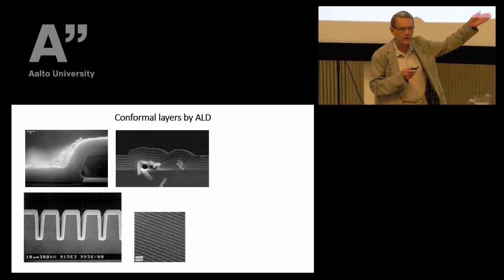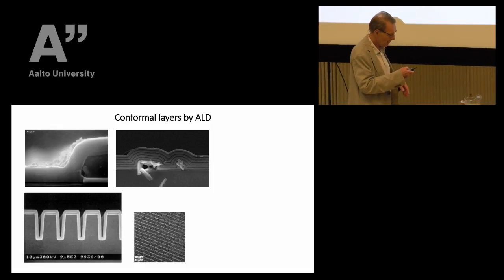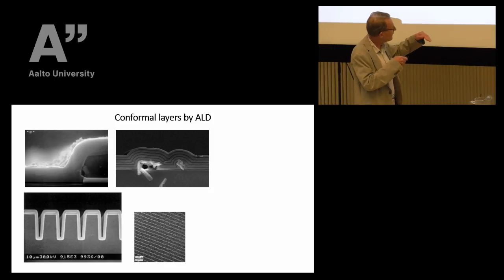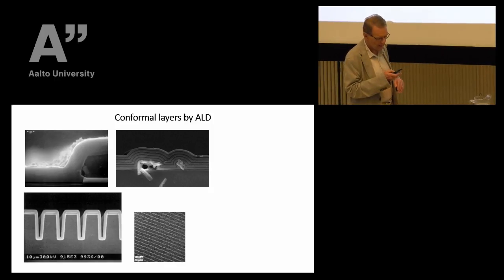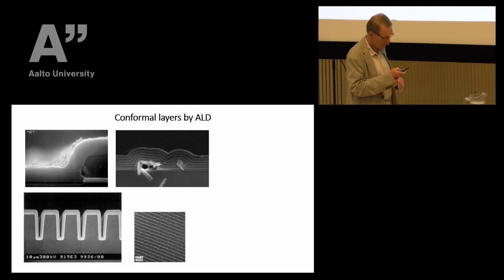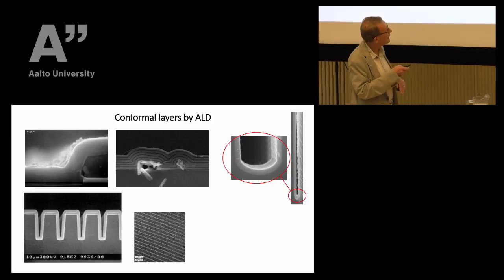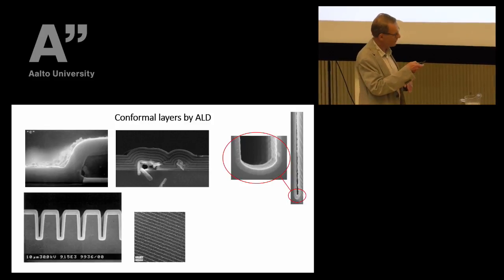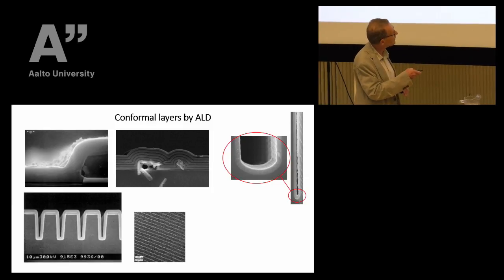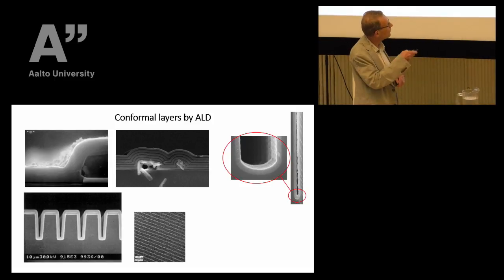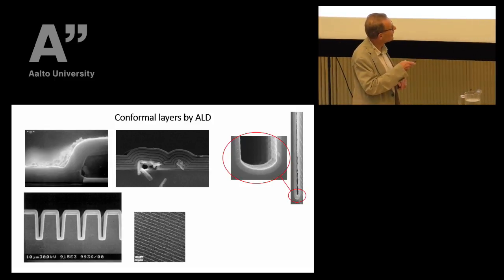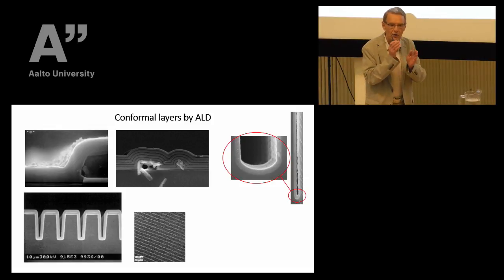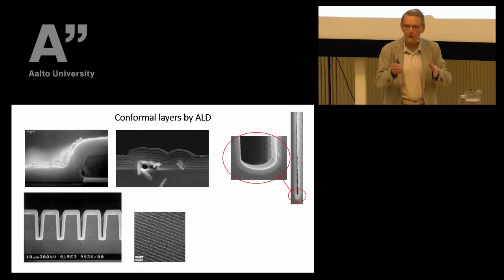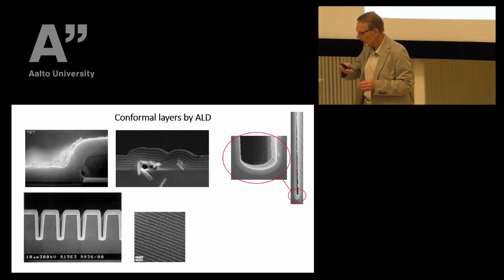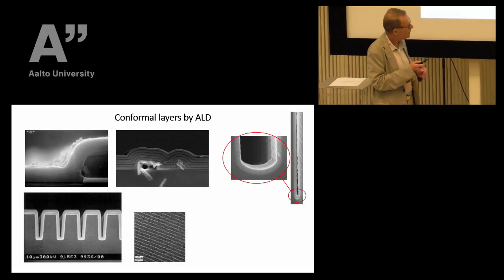Also, we can tailor materials, so it's kind of a superlattice that we can change the material type even at each atomic buildup layer, and we can penetrate even to very deep trenches on the surface, so that you can see the microscopic picture of the bottom of the deep trench here, and it's still extremely uniform. That's one way of increasing the usable area on a semiconductor wafer, for example. That's important in memory chips, where we need a lot of active surface. So this repeats the same.